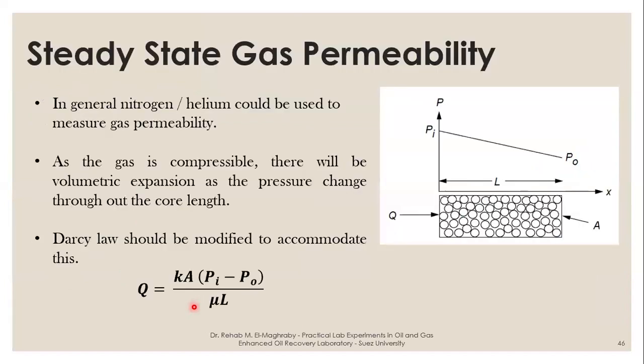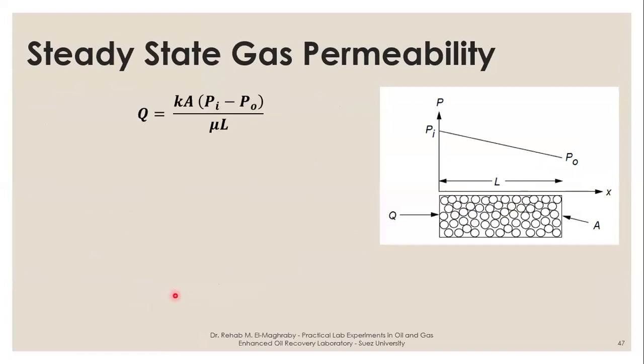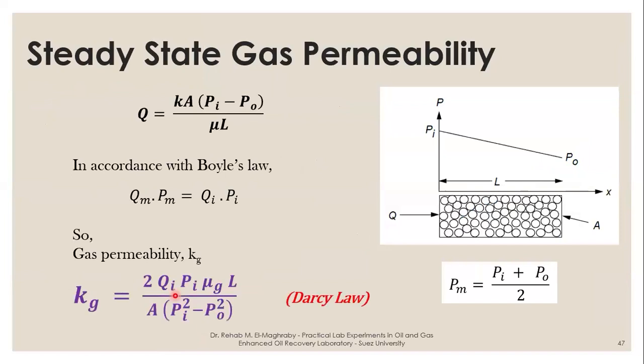The steady state gas permeability is more simple than using liquid, because you can just use a gas cylinder. But we have to reconstruct the Darcy law to accommodate for the expansion of the gas, because with liquid, as the pressure decreases, the liquid will not expand as happens to the gas. So at high pressure the gas will occupy a certain volume, but as you go to the exit of the core, the pressure will decrease and the volume of the gas will expand. To accommodate for this expansion,